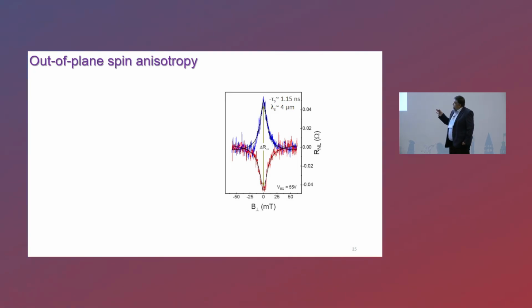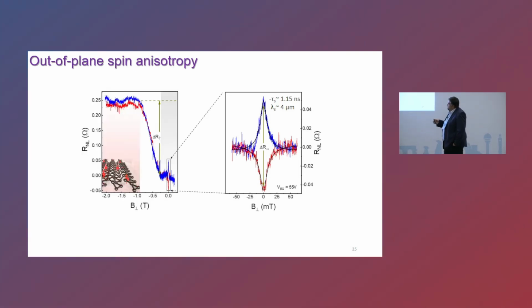Okay, and then we start to study the spin anisotropy. Basically, this is the typical Hanle measurements that I showed several times. Whenever we start to apply much higher fields, then as I mentioned, the injector and detector electrodes' polarization direction is forced to be out of plane. So now you can compare the spin signal while your spins are pointing out of plane versus in